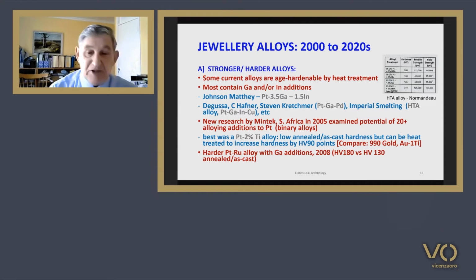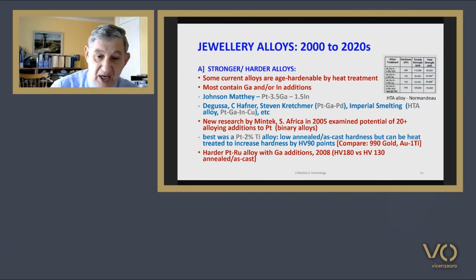Wiesner, in a paper presented in 1999, discusses heat-treatable alloys and notes earlier work at Degussa, at Hafner, Johnson Matthey, and by Steve Kretschmer to develop heat-treatable quaternary alloys, many with melting ranges much lower than the conventional binary alloys, suggesting they all contain gallium and/or indium additions. Such alloys are useful for their spring properties in springs and clasps, for example.